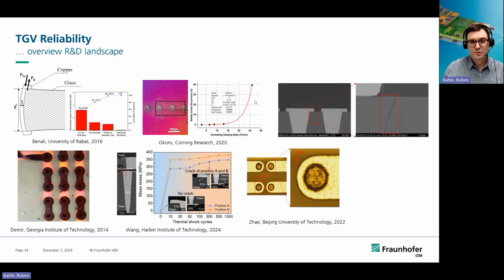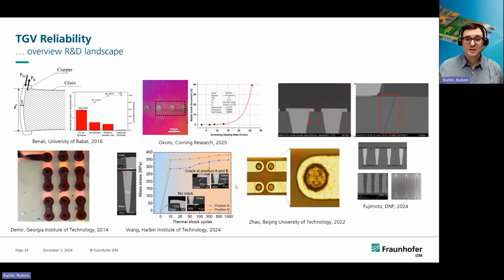If we don't do this, we typically create these cracks directly at the TGV, or surface cracks, because copper is bonding so well to the glass that if you don't have a buffer layer and some intermediate stuff in between to handshake these both materials, the copper will simply shear out some of the glass. And to conclude it, Fujimoto from DNP in 2024 has shown all variants working fine. They have fully filled, conformal filled, one-side filled, and all of them are working really great when it comes to RF impedance and input-output matching, and also some really high TCT values. But these results right now have to get into more RDL layers and into real products.